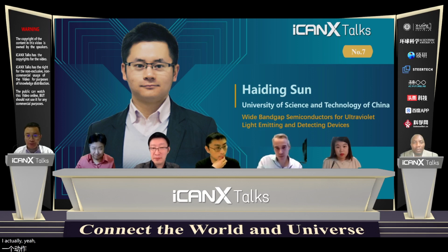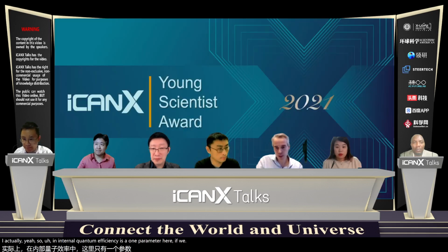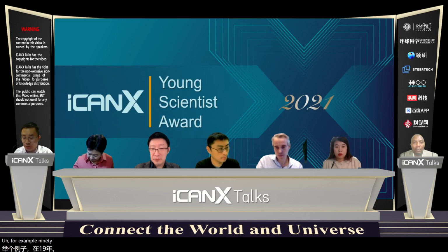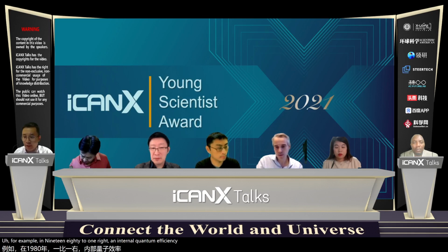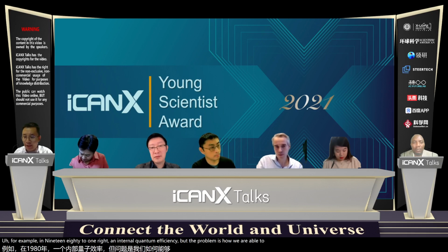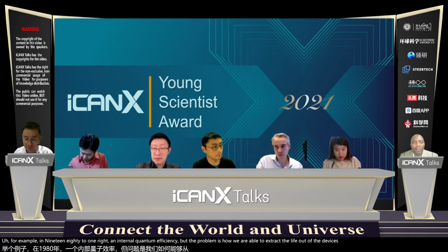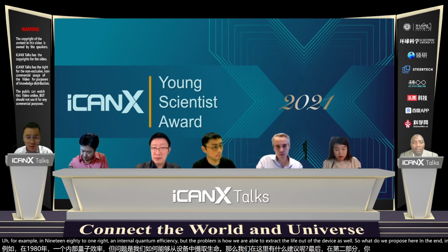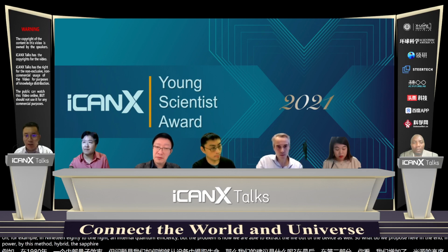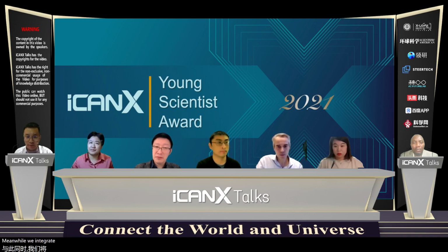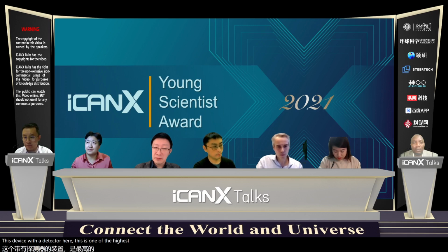Actually, yeah. So internal quantum efficiency is one parameter here. If we get, for example, 90% nearly to 1, right? Internal quantum efficiency. But the problem is how we are able to extract the light out of the device as well. So what we propose here in the end, in the second part, you see, we increase this light output power by this method, hybrid sapphire. Meanwhile, we integrate this device with a detector here.